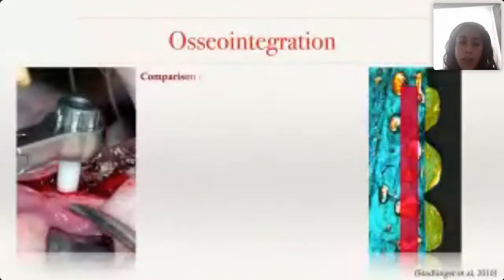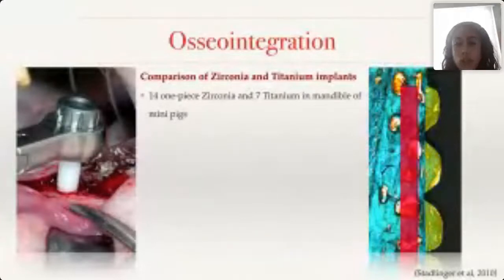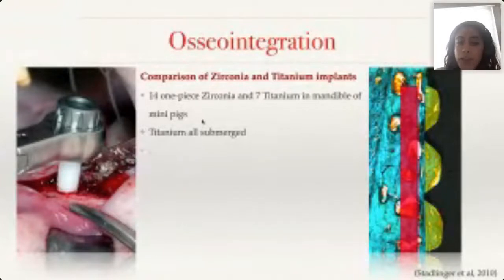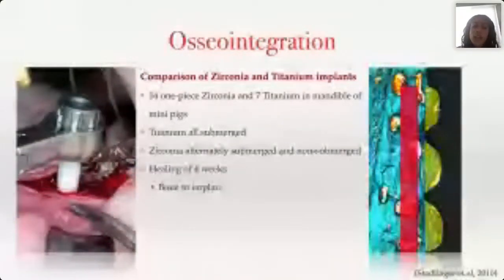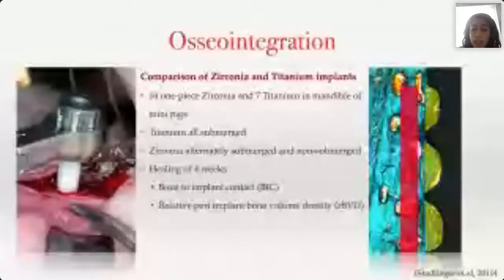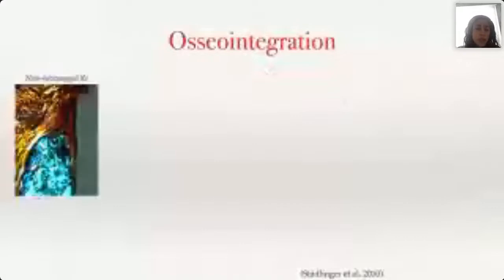This last study on osseointegration, I included because they had really nice histological sections. They had 14 one-piece zirconia and 7 titanium implants placed in the mandible of mini pigs. The titaniums were all submerged, while zirconia was either submerged or non-submerged. Healing was 4 weeks, and bone to implant contact was evaluated, along with relative peri-implant bone volume density, which is the yellow along the threads.